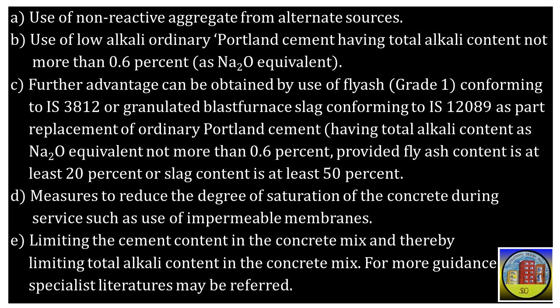A. Use of non-reactive aggregate from alternate sources. B. Use of low alkali ordinary Portland cement having total alkali content not more than 0.6%, as Na2O equivalent.